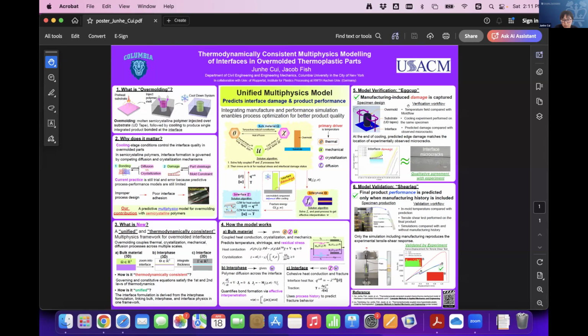And to further validate the model, we use this shear lap specimen, which is designed to test the final product's mechanical performance. A tensile shear test is performed on the specimen, and we compare three sets of force displacement curves: the experiment, the simulation with manufacturing history, and the simulation without manufacturing history. And from this plot, we can see only the result with manufacturing history agrees with the experiment. The simulation without the manufacturing history significantly overestimates the response, which is completely unacceptable. So from this result, we can see that an accurate final product performance requires the manufacturing history.